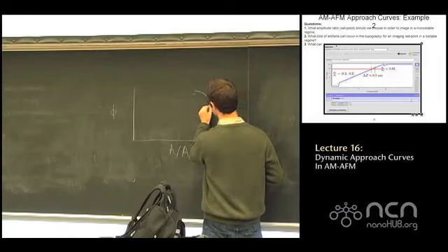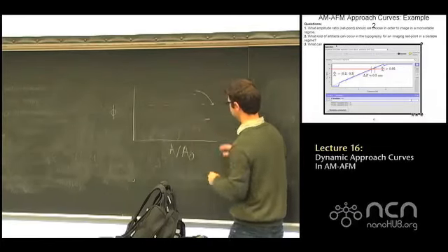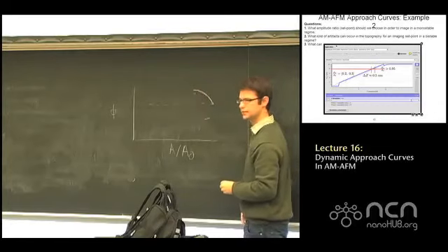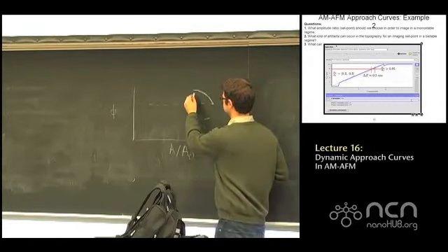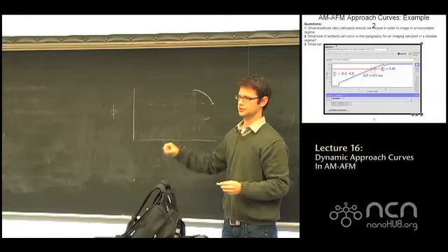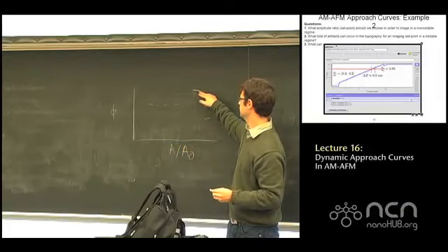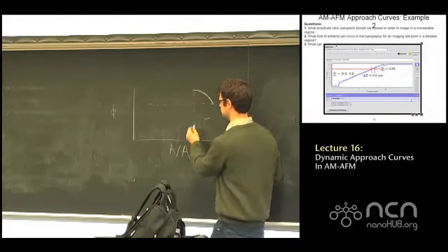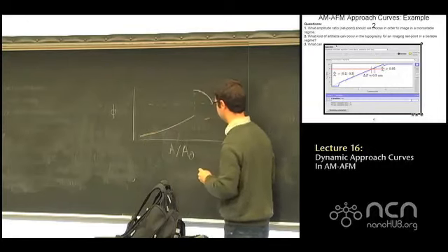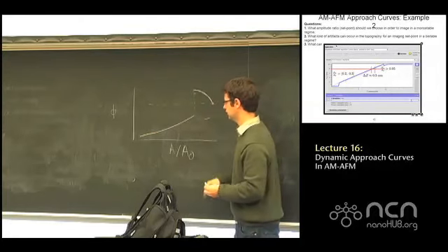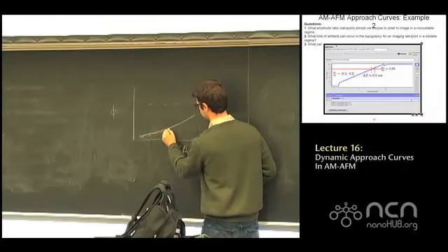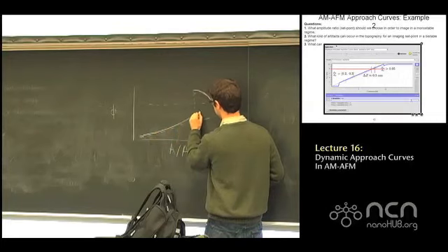Initially it'll increase in the attractive regime, and then there's a jump at some point where we touch the repulsive forces too much, and we jump off the attractive regime oscillations down to a repulsive regime, right? And then on retraction, let's say in dashed line, it will follow something like this.